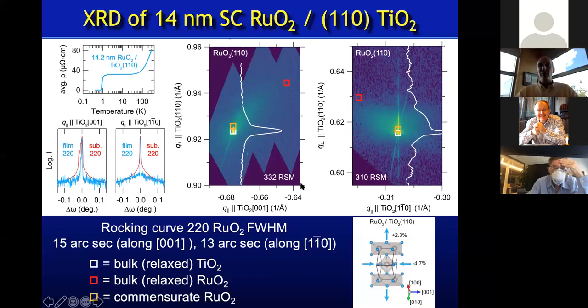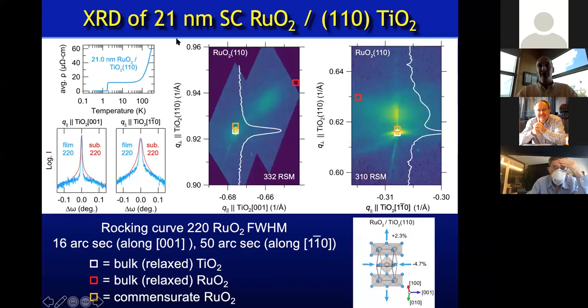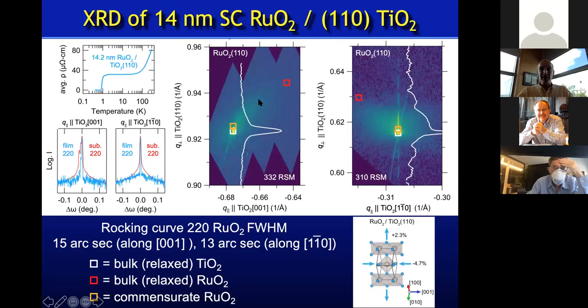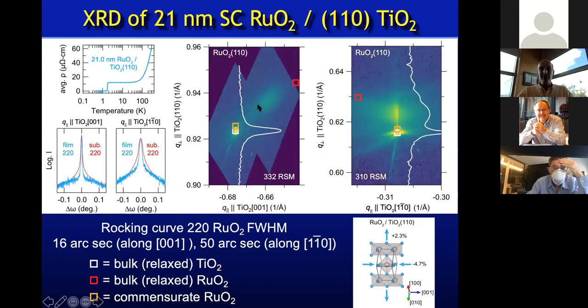And if we make it thicker, so instead of being 14, this is now 21 nanometers, you can clearly see there's a lot of intensity from a partially relaxed film. It's not fully relaxed. I mentioned, from Matthews and Blakeslee, that dislocations don't suddenly come in. They start to relax the film, or there are cracks. So there's certainly a component of the film that is partially relaxed. There may still be some that's commensurately strained. It's hard to see. But as you'd expect, coming back to this one, you see that intensity is missing. But it has a definite effect on the properties.